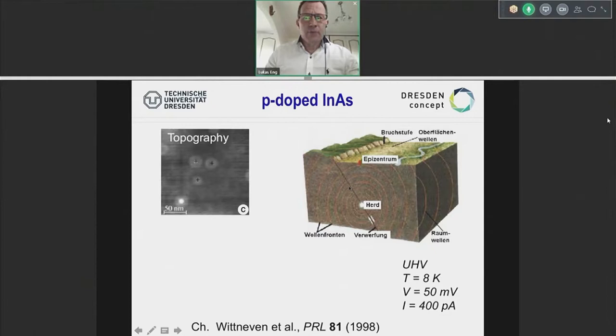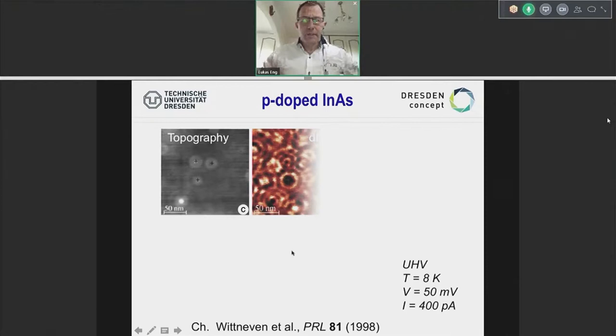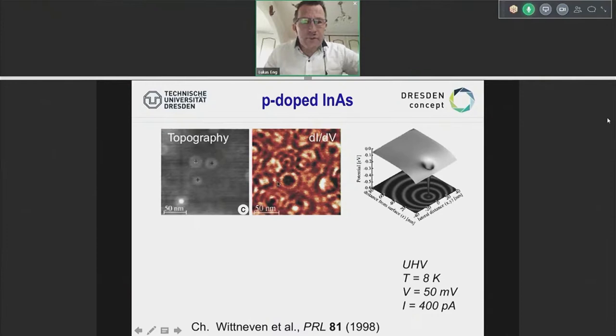And once they propagate, they will at some point cut the surface. You see, this is a surface cut, this is a surface cut. Hence, if you do the math of this one, and you stand exactly on the top right, which is the epicenter, you will get circular waves at the surface. So these are circular waves, in projection. Again, the same thing like a wave function. So they had the splendid idea to take this idea of an earthquake and to do nanoscience. But this is what you see. You see at the surface when you scan with your STM, these kind of circles somewhere. So half circles, circles, and so on, which is really very weird stuff.